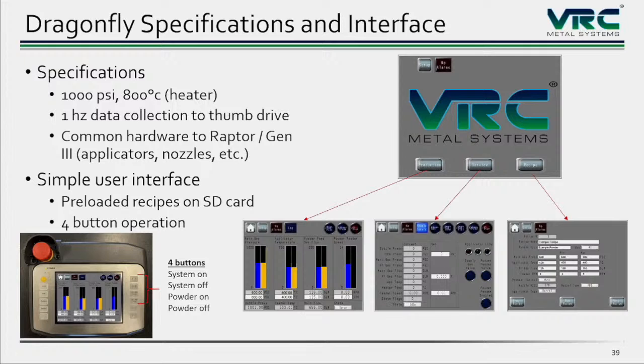So here's the functionality of the pendant itself. Oh, by the way, the system still has the same performance characteristics of 1,000 psi, 800 C as the regular systems. But in this case, one of the unique parts about this pendant is it's preloaded with recipes. So in this case, you don't get, like Vic was saying, you get a cold spray system, now you can't run it, right? You need to learn how to run it. Well, in this case, it's preloaded with certain recipes so that once you get it, you can immediately go in, select those recipes. They're pre-qualified. We give you data sheets with them so that you know what you're supposed to get at the end. And then you can start going, and the operation is very simple. It's a 4-button operation. Once you select your recipe, you press one of 4 buttons to start the system, stop it, turn the powder feed on and off, and that's it. So this is very turnkey, getting back to your point, very turnkey for people in the field.